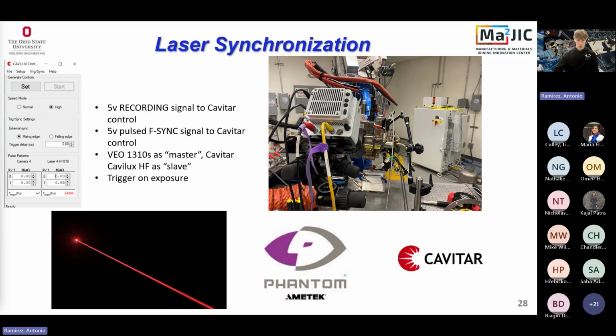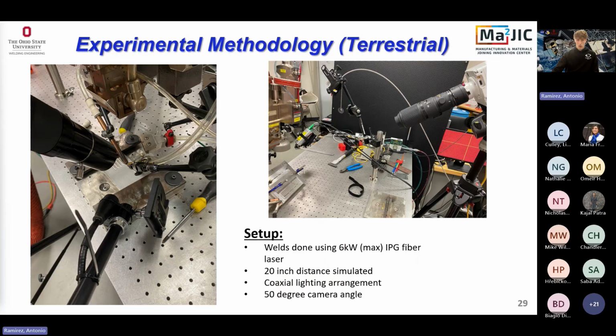An F-sync signal to sync with the laser, and then a recording signal to start recording, and then the camera will start triggering on laser exposure, basically. For terrestrial welds, we used our 6 kilowatt max power fiber laser. We simulated that 20-inch distance, and we had a coaxial lighting arrangement instead of the cross lighting arrangement we had earlier. And then we had a 50-degree camera angle to try and get as orthogonal as possible to the melt pool.